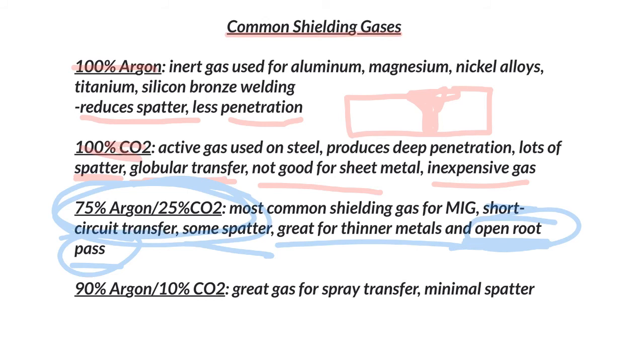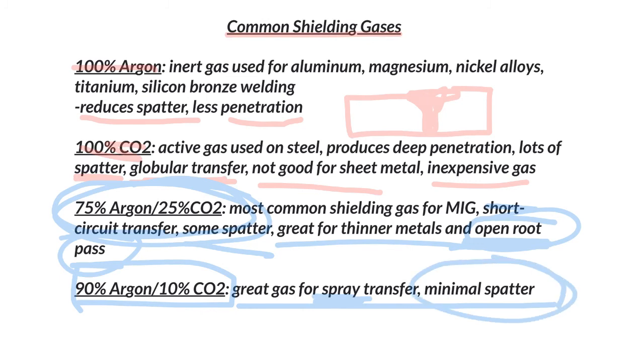Okay, 90/10 is a mix of 90% argon, 10% CO2, and this is a great gas for spray and also pulse spray transfer. Spray is a super hot welding process. You can just fill up weld joints super quick using larger wires. It's actually a great metal transfer mode for MIG, almost no spatter other than usually at the start because the wire hits and creates a really big explosion. But then after that, it sprays, it's quiet, not a whole lot going on. I got a whole video on the transfer modes as well.